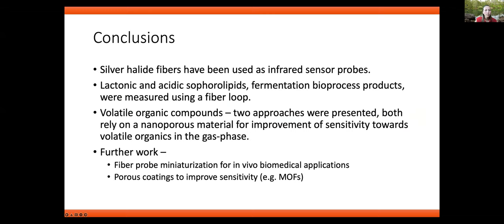So I will conclude now that in this work, we used silver halide fibers for infrared sensor probes. We could distinguish lactonic and acidic sophorolipids, which are fermentation bioprocess products. We also showed that we can measure volatile organic compounds with two different approaches presented. And our future work in this area is focused on miniaturizing those probes. And this is really important for biomedical applications where you want to insert the probe into different tissues. At the moment, the commercial probes are way too large for such applications.